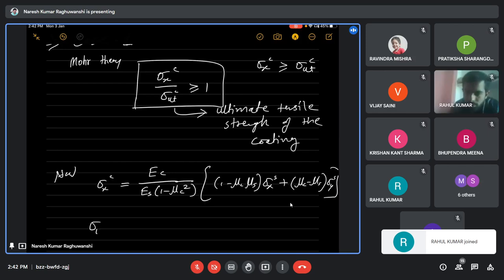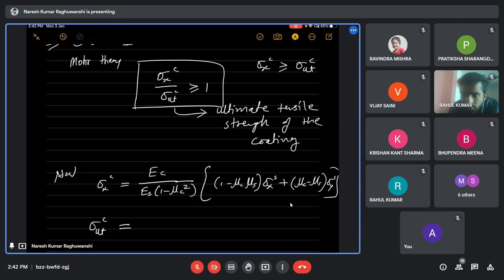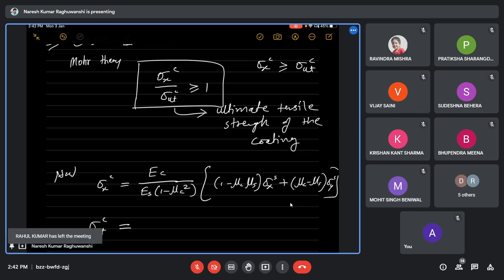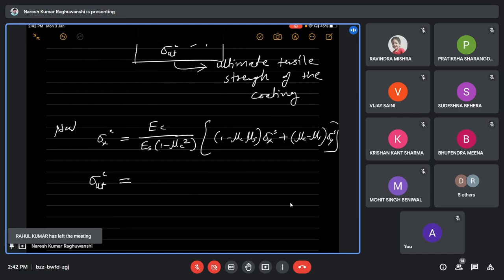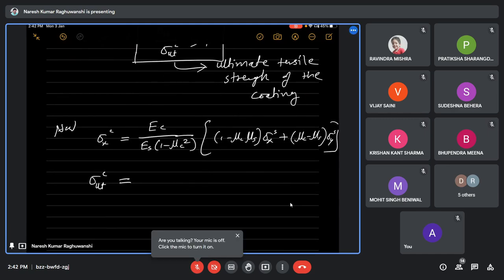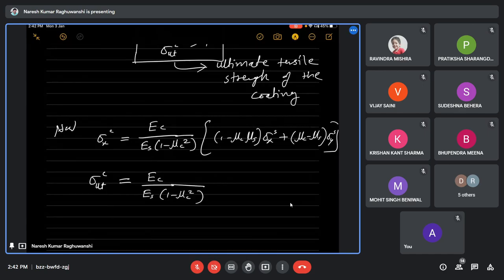And the ultimate tensile strength formula, according to this. The ultimate tensile strength we will find by simple tensile testing on the UTM. So in the UTM, sigma y is zero. In that case this formula is EC upon ES, 1 minus mu C square, and 1 minus mu C mu S sigma X star. And sigma y term is 0. And sigma X S equal to sigma X star, and this is the minimum stress to initiate the crack.